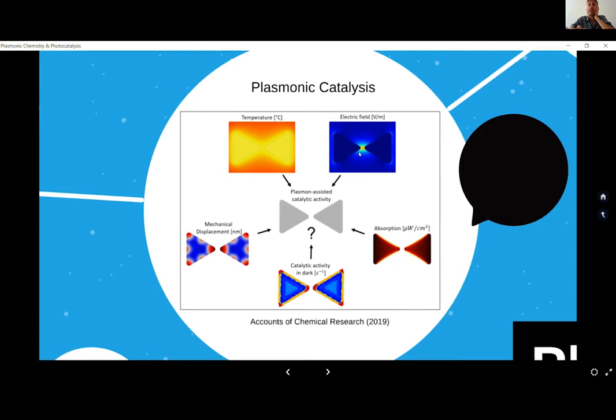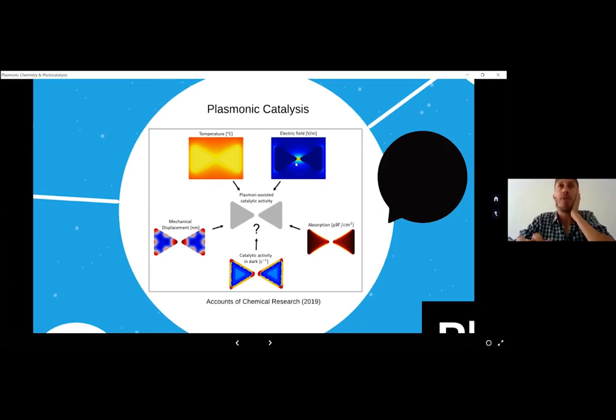But as Anatoly mentioned at the very beginning today, for a long time, there was a lot of complaint in the community that plasmonic was a really lossy material and that we were not using that kind of property, right? So the plasmon relaxation and the energy that is being dissipated to the environment after the plasmon has been excited and how we can use that. And indeed, for chemistry, that's really important, right? Because besides the electric field confinement that happens in the hotspots of plasmonic nanoantennas, these materials also absorb part of the light, and that absorption creates energetic carriers inside the material, right? These hot carriers, hot electrons and hot holes. And also at the end, these highly energetic electrons dissipate the energy through the phonons of the material, right? So we have mechanical displacements in the material and we have electron-phonon coupling. And finally, we end up heating the structure by increasing the temperature. So all these things happen at the same time.